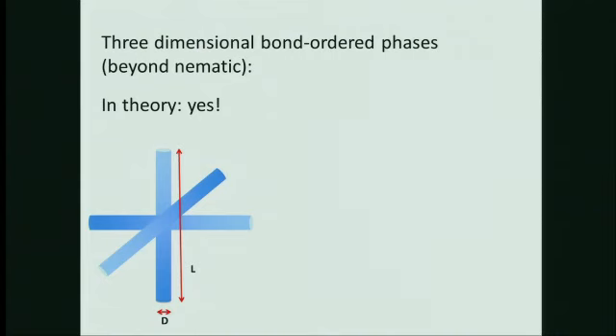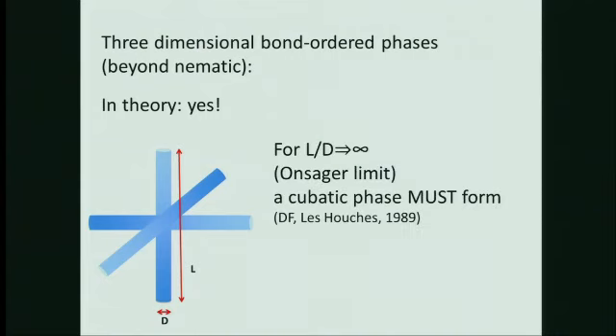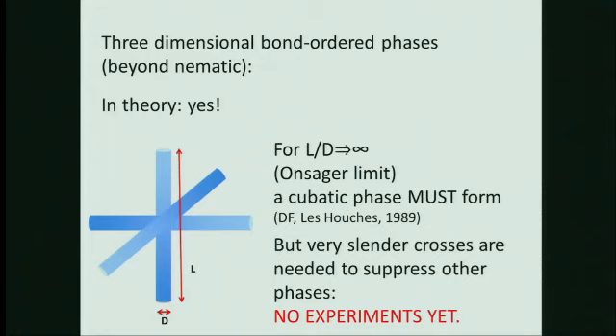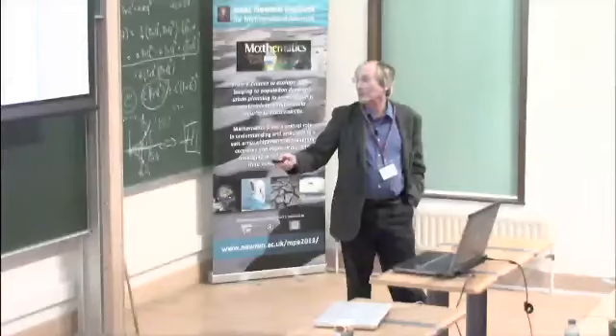And so it's easy to show that this should happen, but the only thing is that in practice it doesn't happen so easily, because you have to go to really very high densities, and density in this case means the number of particles in a volume L squared d, which is order the excluded volume. And that number of particles has to be of the order of 50, and at the same time you want the number of particles per volume, which in these units would be the number of particles in the volume L d squared, to still be very, very small. And to get that, you need huge aspect ratio. So you need this limit, and that means that it's extremely difficult to get, and so there are no experiments yet.